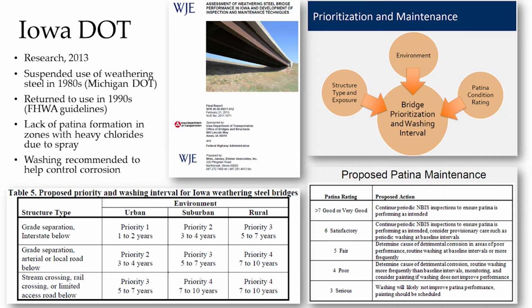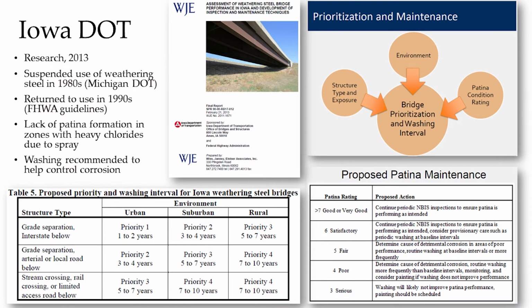Iowa did a study of their bridges in 2013. They came back and said, yeah, salt accumulation can be a problem, so they came up with these recommendations for washing, depending on the structure type, whether it's a grade separation, interstate below, local road below, or stream crossing, and urban, suburban, or rural, with different priority. The recommendation was that if they have a bridge in an urban area with high traffic, be sure to clean it every year. Otherwise, salt will accumulate and potentially give you that durability problem.